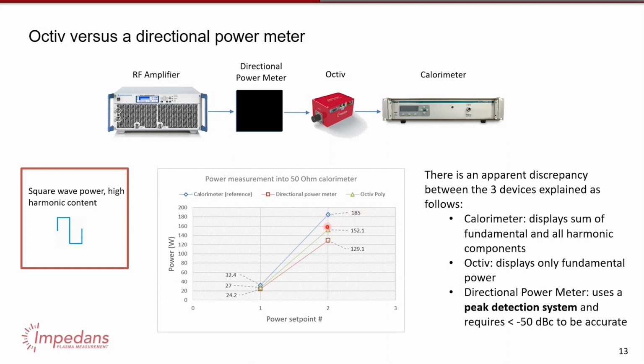The Octiv VI probe was measuring 152 watts in the fundamental frequency, the 13.56, so not the harmonics yet. But the directional coupler, which doesn't try to split out frequencies or anything, only measured 130 watts, so it is completely wrong. So harmonic content damages the data basically.